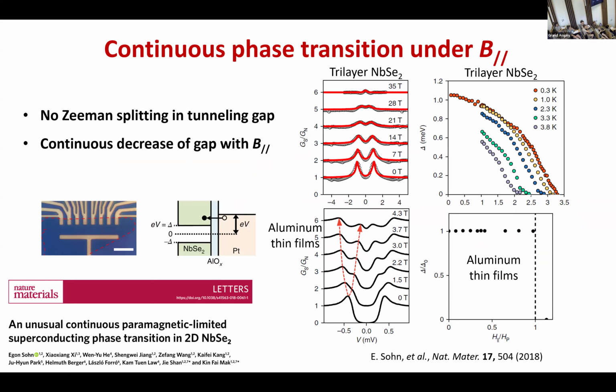After the first standard transport and resistance measurements, people also tried to see how the gap of the system evolves. We have our organizers also as experts on this. So in this paper, they measured tri-layer niobium diselenide, and compared it with aluminum. What they claim is that by applying an in-plane magnetic field, the superconducting gap closes, but it evolves with the in-plane field in a continuous way, as it looks in their plot here. So it looks pretty different from the aluminum thin film.